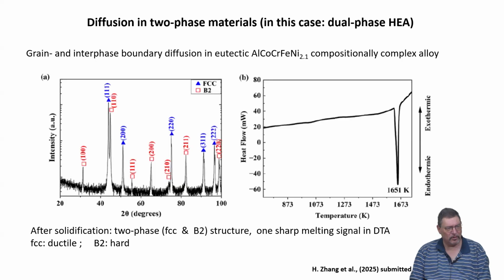What we took is dual phase high entropy, so it means like a eutectic high entropy system, right? And you can see here that we have eutectic between an FCC and a B2 system. Obviously, this would also be nice and good if you think of the mechanical properties, because you basically have a ductile and a hard phase again. And it's only this two-phase solid solution which we have. And we have single-phase sharp melting because we have a eutectic alloy, right? So this means all the phases which take place are participating and melting together.